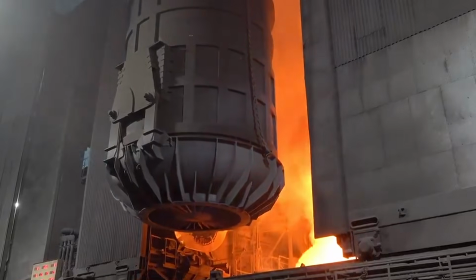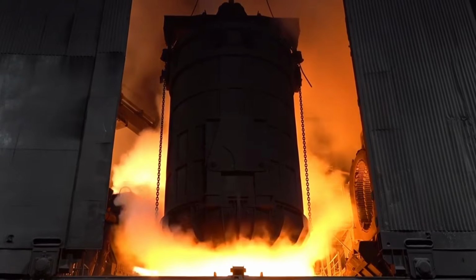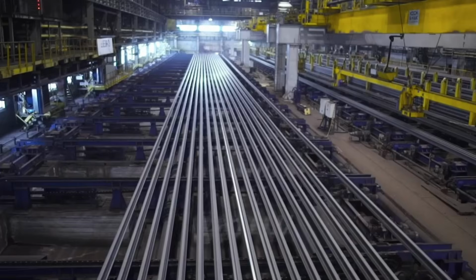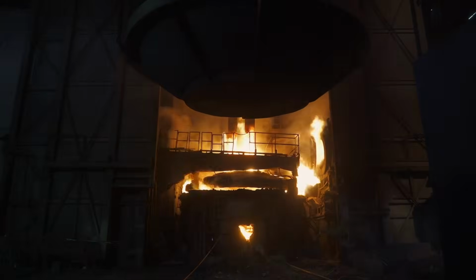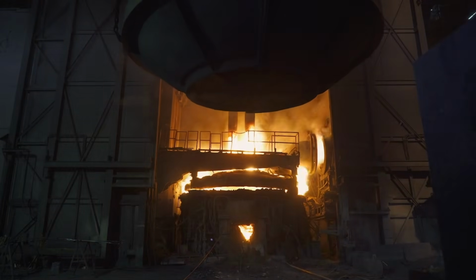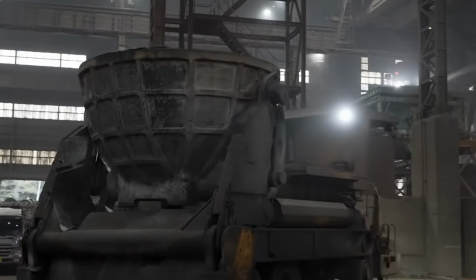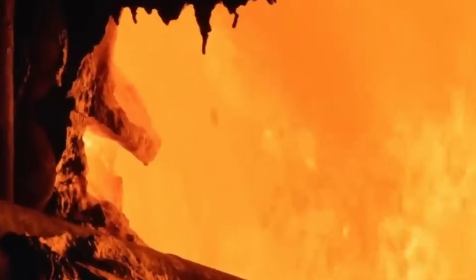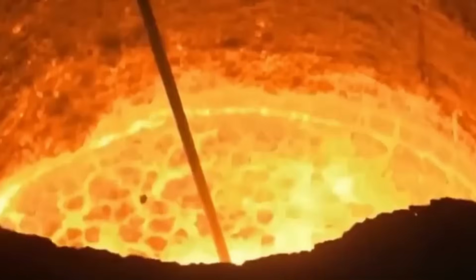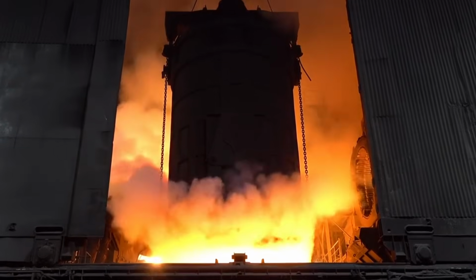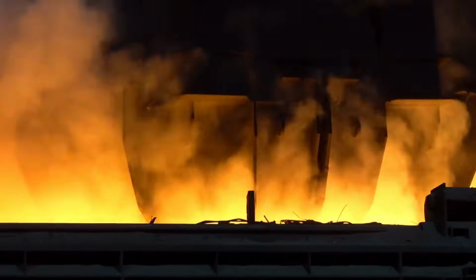Refined molten steel flows into continuous casting machines that form solid billets. The caster pours liquid steel into a water-cooled copper mold that solidifies the surface while the interior remains molten. As steel solidifies, it's continuously pulled downward at 3 feet per minute. The emerging billet measures about 12 inches square and stretches hundreds of feet before cutting.